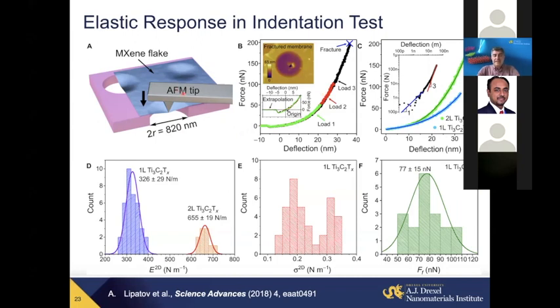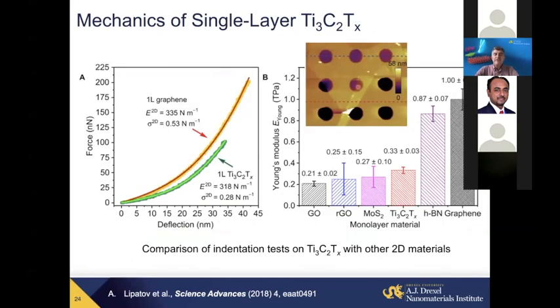Those are mechanical tests conducted in collaboration with Professor Sinitskii from the University of Nebraska-Lincoln, showing that MXene single-layer and double-layer flakes have very high moduli. He tested a number of materials. And what is important, when it breaks, there is no catastrophic failure. You see, this is a suspended film of MXene over a hole in a silicon support, and you can see this small tip going through the membrane. The membrane doesn't fail. A graphene membrane would explode when this happens. So it means also graceful failure, which is important.